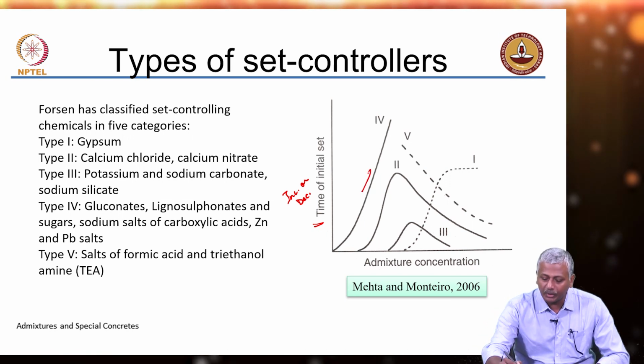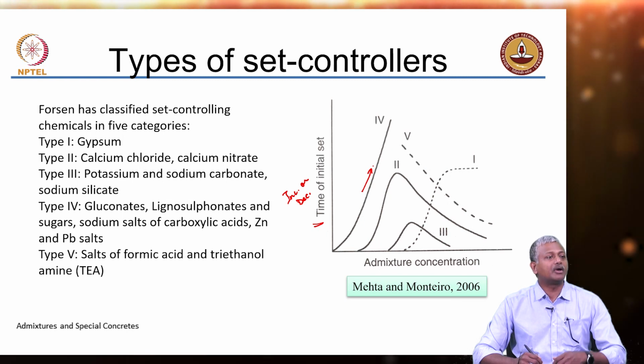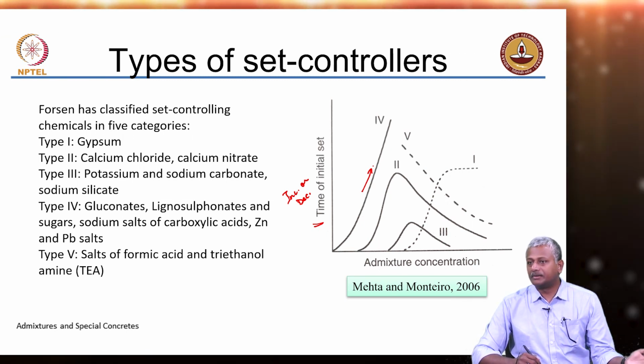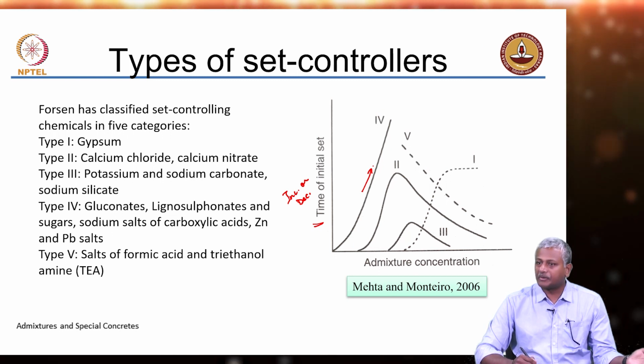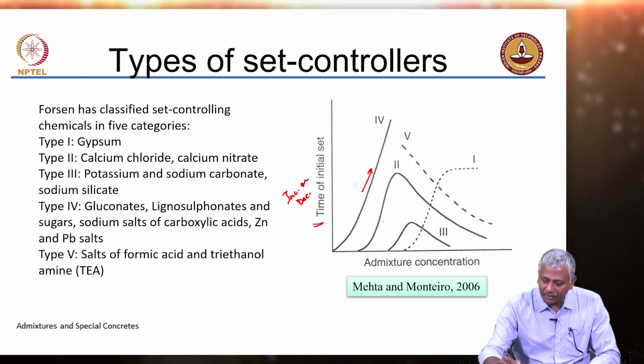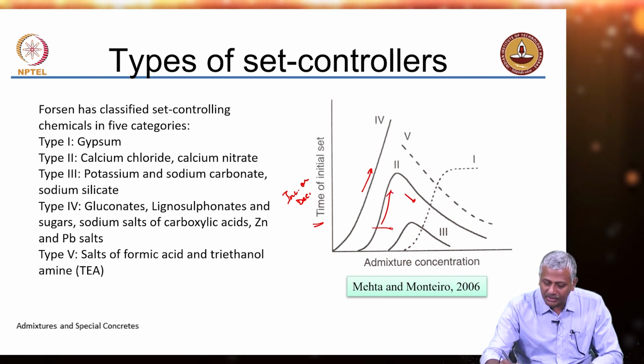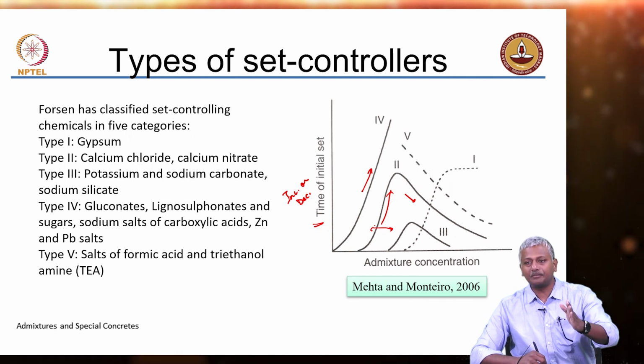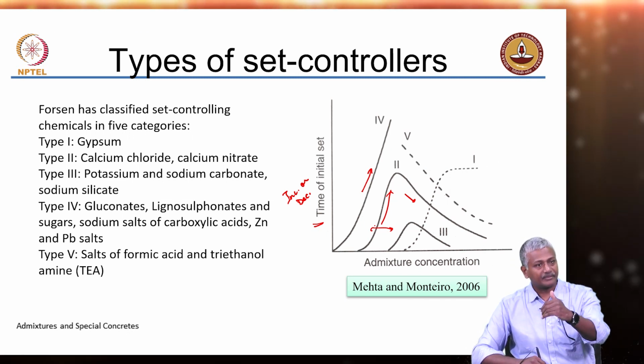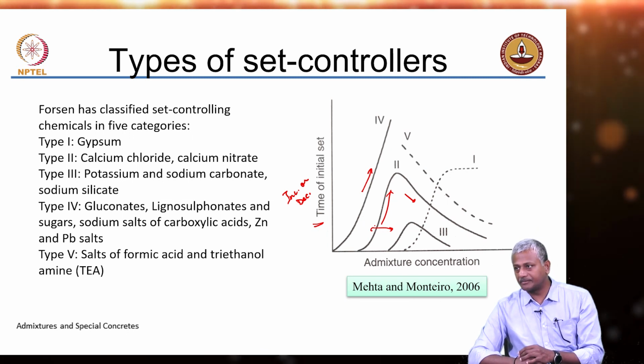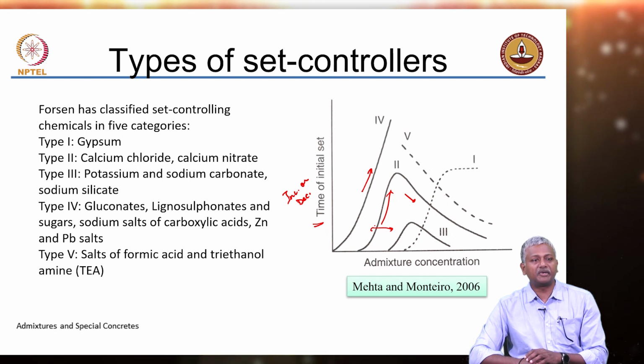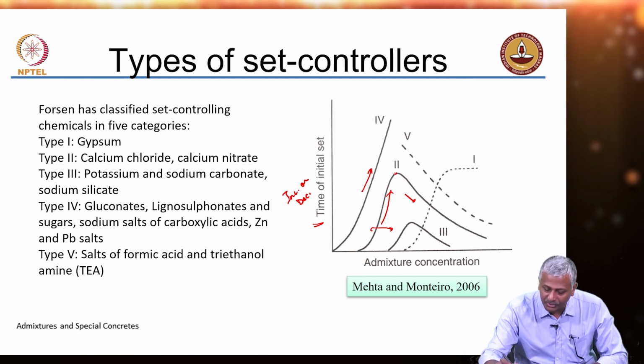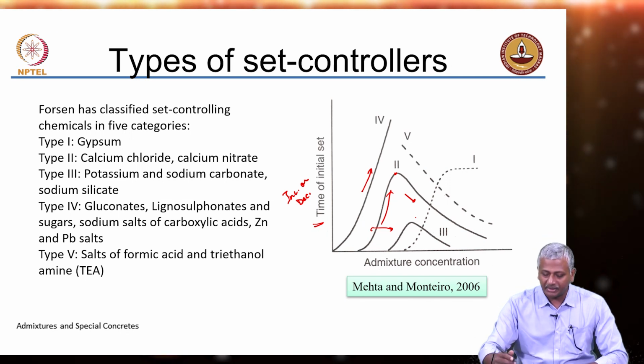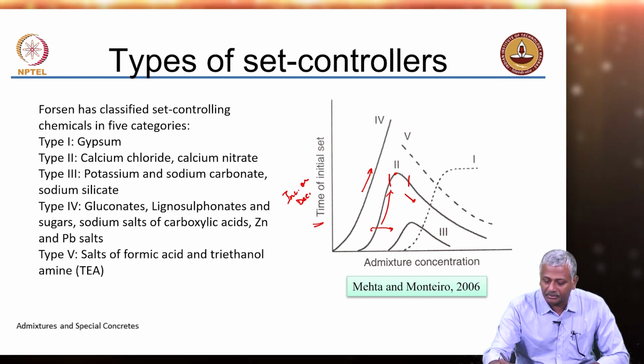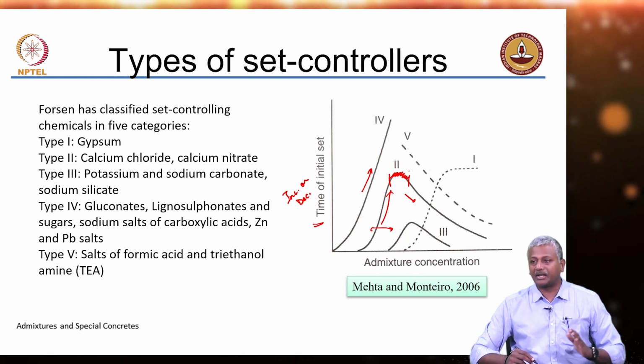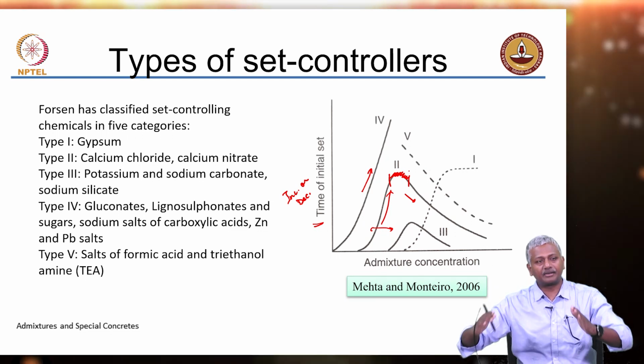Which means that if the curve is going up, that means my initial set is going on increasing as compared to a mixture without any admixture, without any of these chemicals. If it goes up and comes down, that means at small dosages there is increase in setting time or retardation, at high dosages there is reduction in setting time or acceleration. Okay. So, that is how this curve needs to be interpreted. It does not mean that your setting time goes up to a certain point and then starts dropping, it is not like that. So, you can almost think that you can almost remove this part of the curve and think that okay, at one concentration you are leading to retardation, at another concentration you are leading to acceleration.